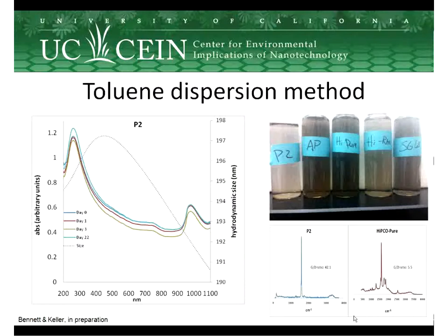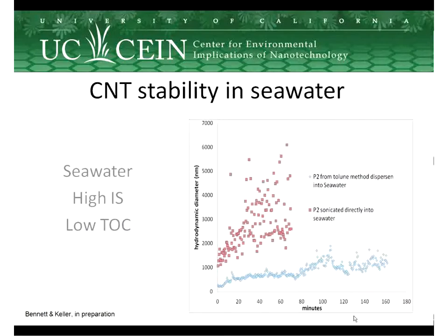What is the primary size, and how does the shape of the particles affect that measurement? Right. The primary size is a few nanometers, on the order of about 5 to 7 nanometers in diameter, and it ranges from 700 to 1500 nanometers in length. So this is kind of an average. Yeah, sort of. Kind of a weird average. Still trying to figure that out.